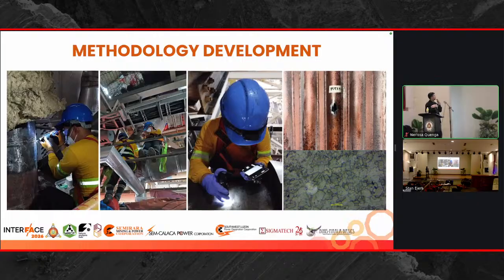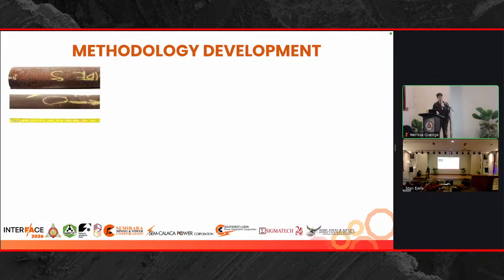So this is an example of a boiler tube and the replica, the microstructure that we were able to extract during our field activities. So for our in-house laboratory testing, we generally start with the non-destructive testing, which is initiated by visual inspection of the as received sample. So we look for failure or degradation features such as corrosion or initial cracking or bulging.